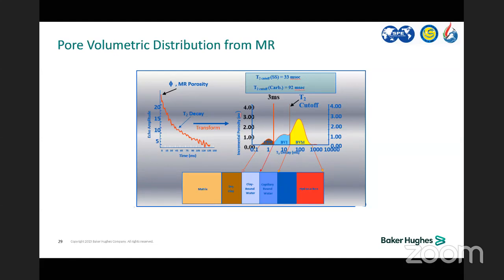So you can see this cutoff requires calibration from lithology to lithology and from field to field. We should not count on the standard and then blame why the free fluids or the permeability from NMR is not matching my core data, or not matching the mobility from the formation testing. We have to identify the right cutoff first and then look at the results, because everything is calculated based on your cutoff, and the standard cutoff varies from rock to rock, reservoir to reservoir, and field to field.